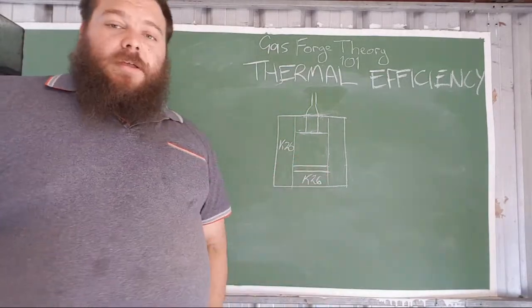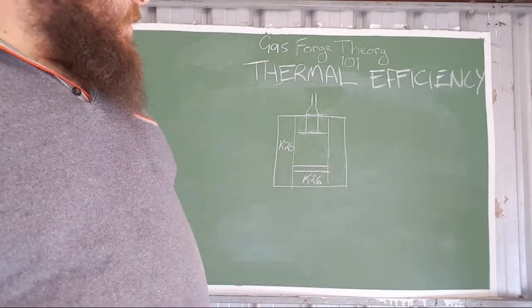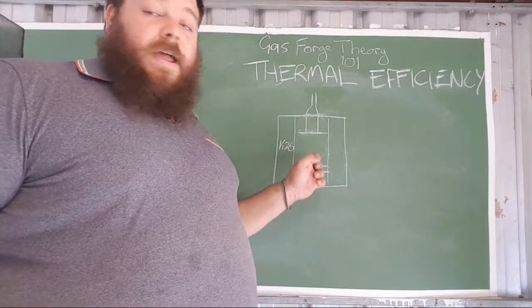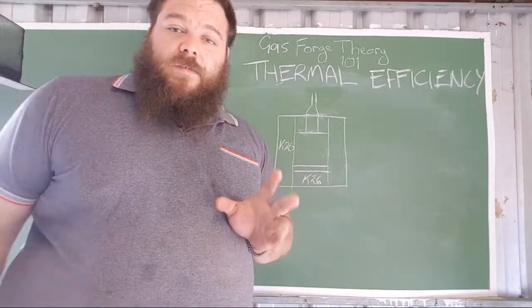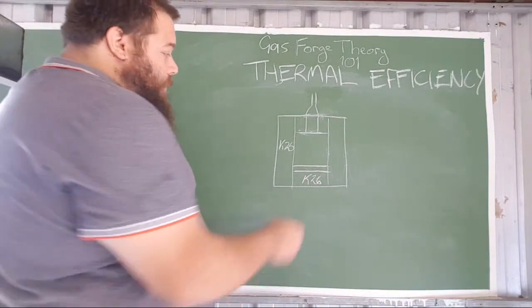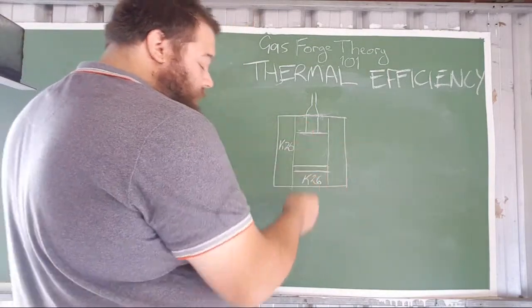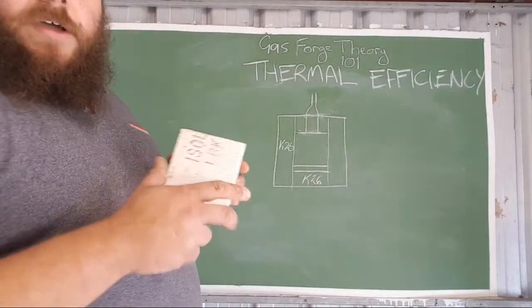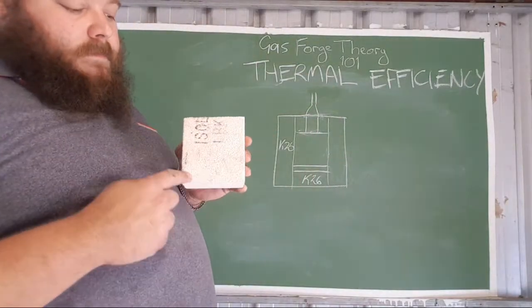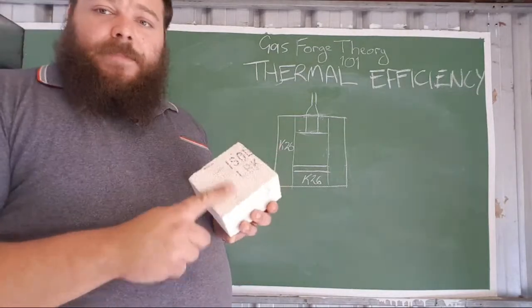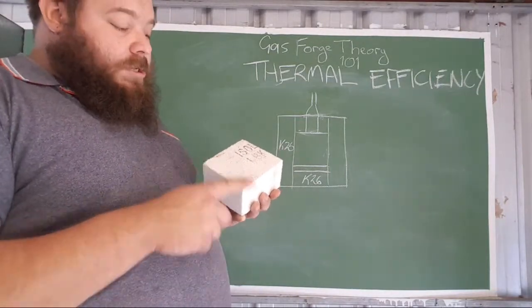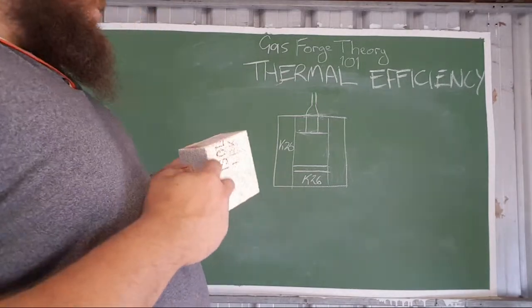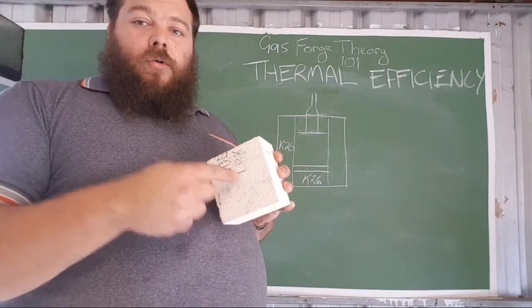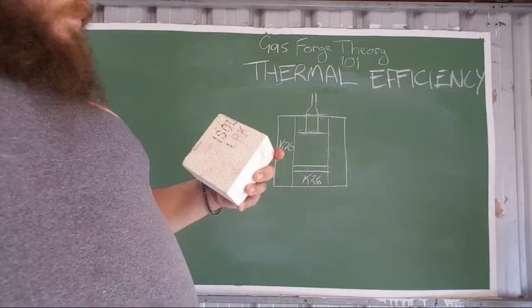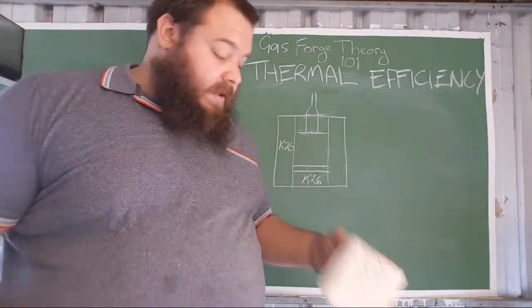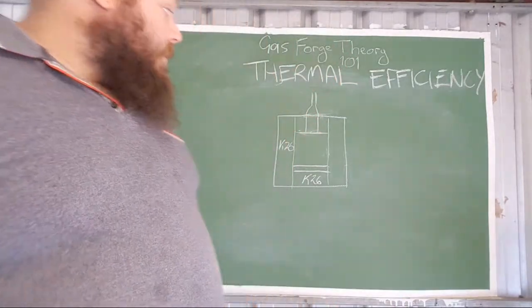So be very, very careful to have a higher density refractory as your forge lining. And I have actually been converted, and I wasn't before, to painting the internal surfaces of your Isowool bricks with Satanite. Painting them with a layer of Satanite lowers the porosity, which means it increases your reflectivity because you have no captured heat. It also protects them slightly. It hardens the surface. So that is something to think about if you're making a brick forge.